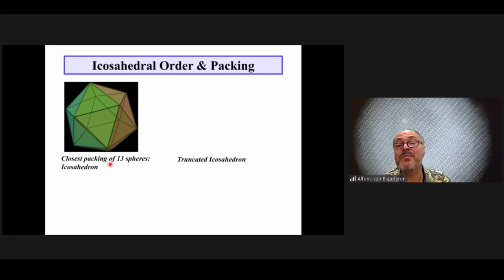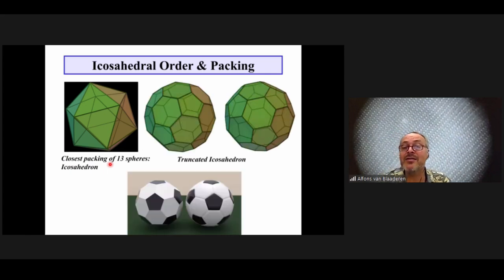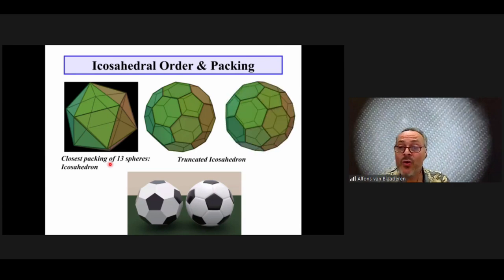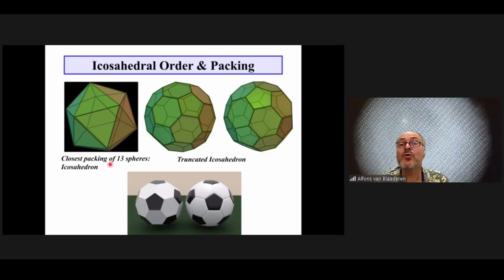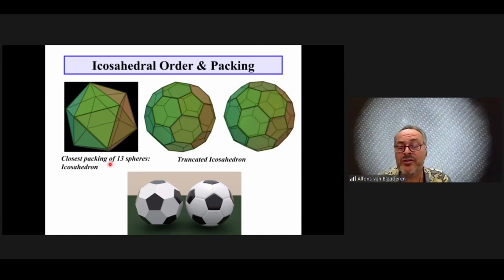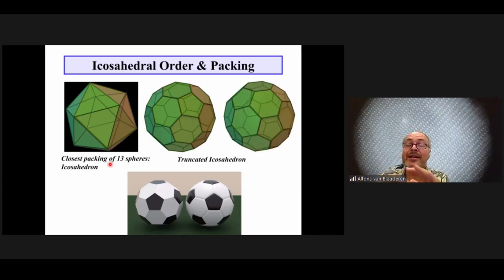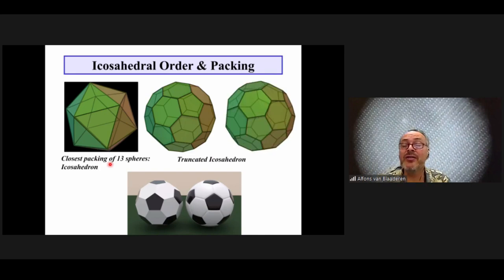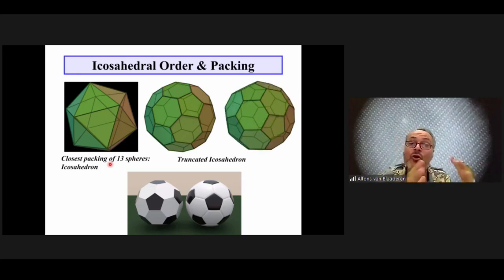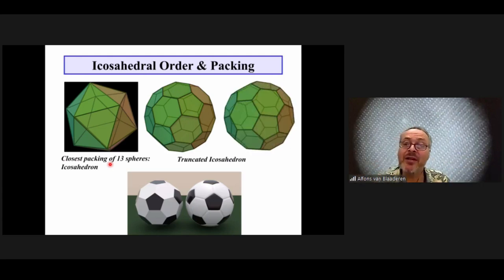The cut-off structure of an icosahedron everybody knows as a soccer ball, but that happens also when we start to do self-assembly in spherical confinements. We get icosahedral structures and truncated icosahedral structures. So it was well known that the closest packing of hard spheres is this icosahedron, and even for many different pair potentials like the Lennard-Jones potential, that closest sum of distances also translates itself into the free energy of Lennard-Jones clusters, and therefore also of metals, for instance, gold or silver, being better with this icosahedral symmetry than for the bulk FCC crystal. So that was known.